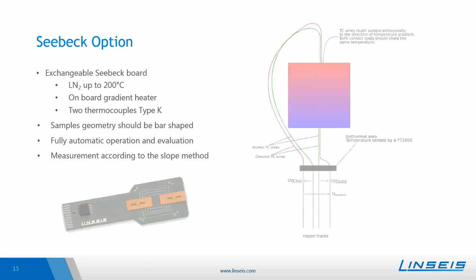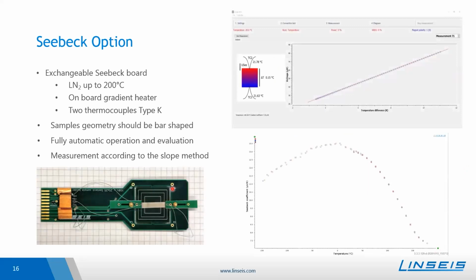On the next slide, you see a sample inserted into the board. You see the contacts of the thermocouple wires and the rectangular bar-shaped sample. The temperature of the cold side and the temperature of the hot side are calculated using the thermal voltage of the thermocouples, and the absolute temperature measurement is performed by a PT2000. The thermocouple wires forming one thermocouple are very close to each other and therefore minimize the temperature measurement errors due to temperature non-uniformity of the two contact spots. The Seebeck voltage is then measured between both negative thermocouple wires so that the Seebeck voltage occurs in the exact same spots where the temperature is measured.